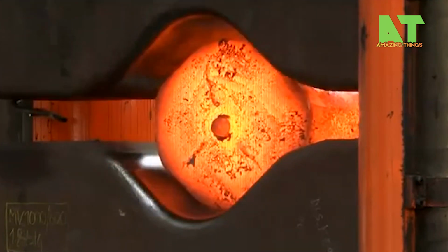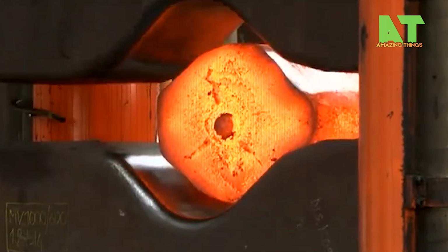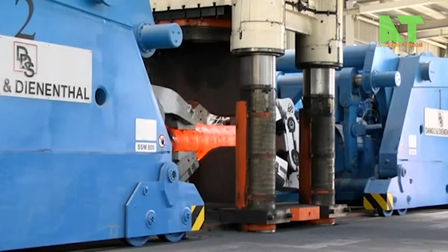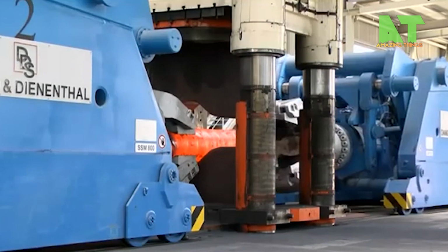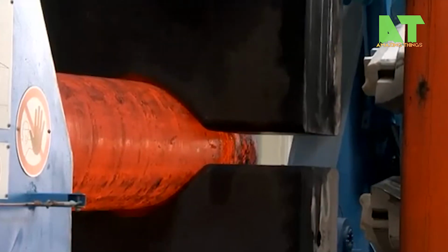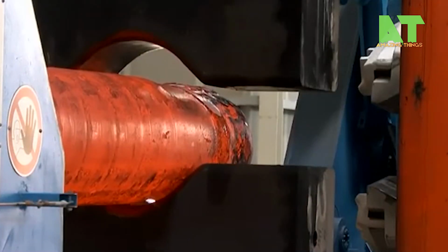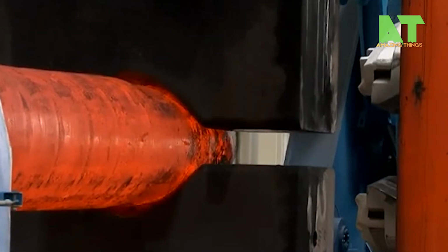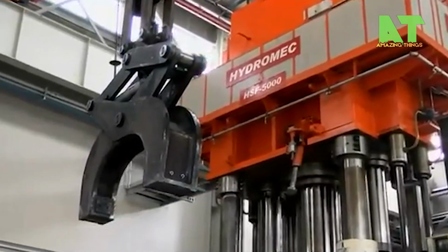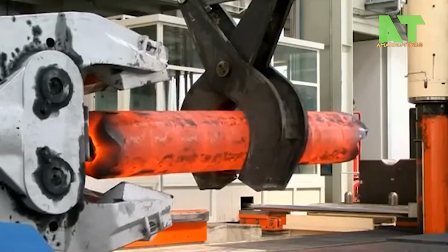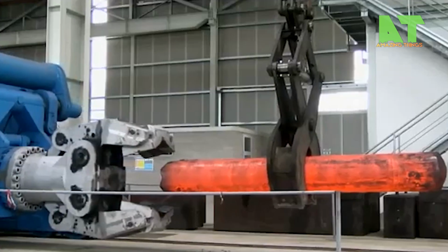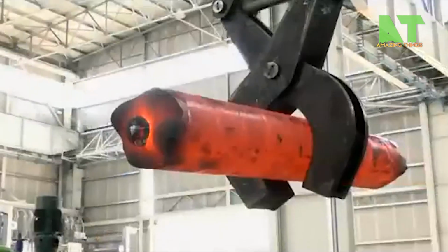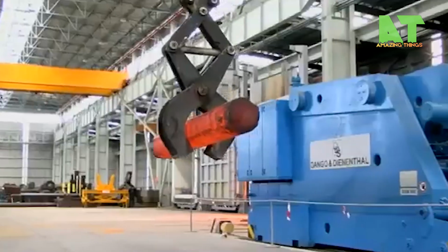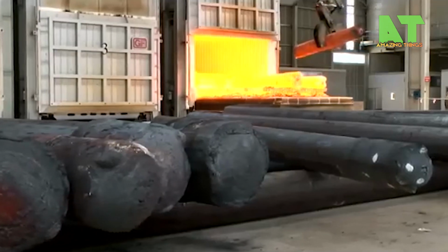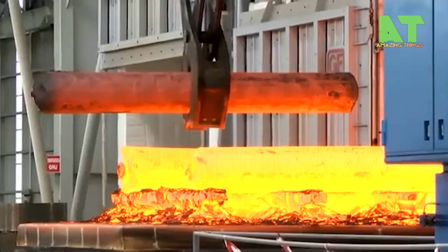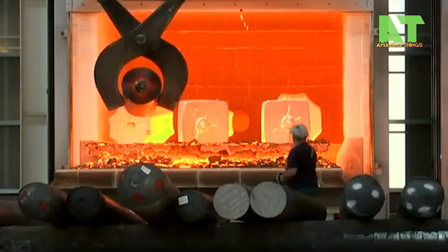50 degrees can make the difference between perfect grain structure and a rejected piece. Now watch as that glowing billet moves to the forging press. What you're witnessing is open die forging, where massive hydraulic hammers weighing dozens of tons strike the steel repeatedly. Each blow isn't just shaping the metal, it's actually refining the internal grain structure, aligning the crystalline structure for maximum strength. This is fundamentally different from casting or machining. Forging creates parts with superior mechanical properties.